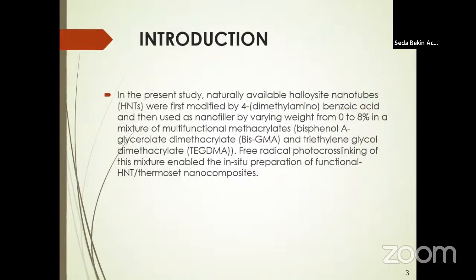So, first of all, in the present study, naturally available halloysite nanotubes were first modified by 4-dimethylaminobenzoic acid and then used as nanofiller by varying weight from 0 to 8% in a mixture of multifunctional methacrylate monomers. Free radical photocrosslinking of this mixture enabled the in-situ preparation of functional halloysite thermoset nanocomposites.